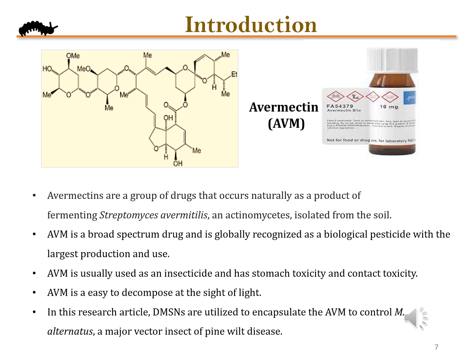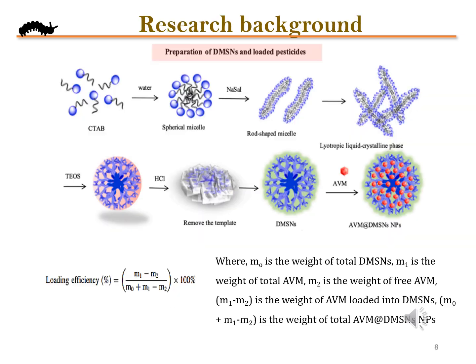In this research, DMSNs are utilized to encapsulate the AVM to control Monochamus alternatus, a major vector insect of pine wilt disease. The research background: here CTAB was used as a surfactant or templating agent, which forms a micelle-like structure. Later, TEOS was used as a silica source, and the template was removed using concentrated HCl.